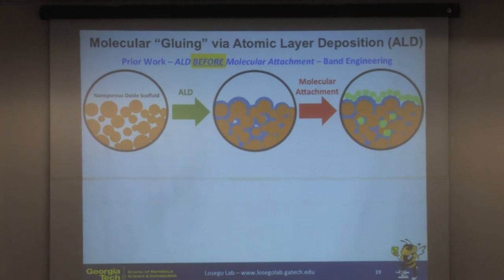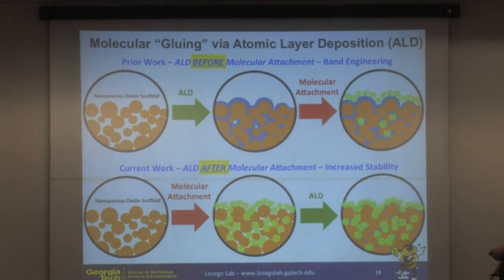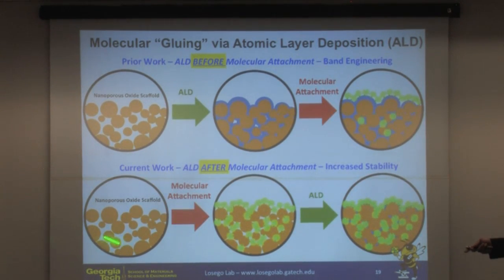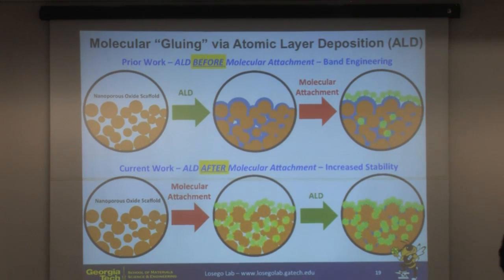Okay, so I will say, and to be very clear, there has been work done previously where people have taken nanoporous oxide scaffolds, applied an ALD coating, and then attached the molecule. And this is really to understand the photophysics of electron transfer between the molecule and your nano-oxide scaffold. So putting insulators or conductors in between, changing the thickness. So people have done that previously. What had not been done previously was to take the scaffold, apply your molecules, and then do the ALD deposition.